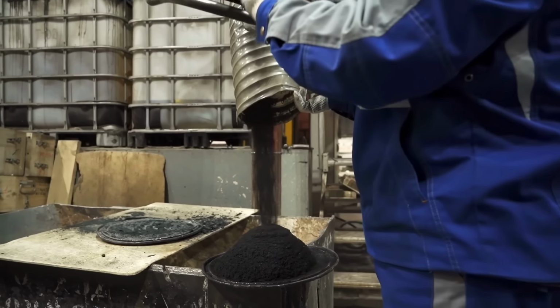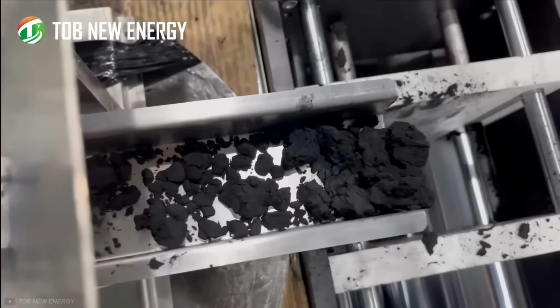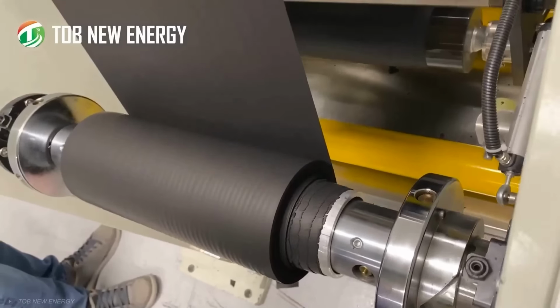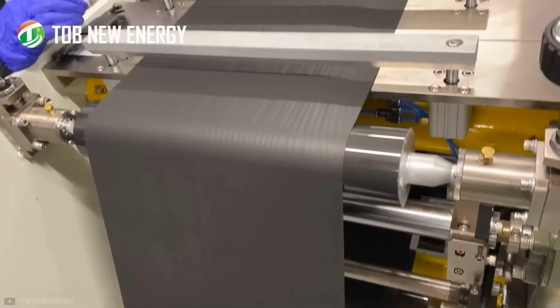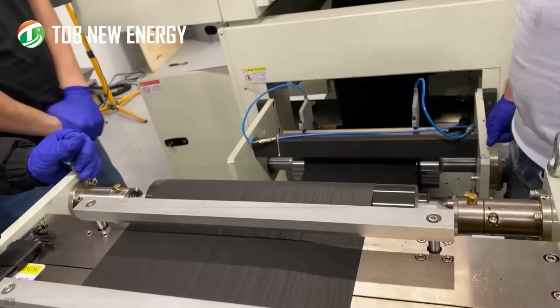But now back to how Tesla cracked dry electrode manufacturing and what that means for cell performance. Okay, so from my research, the big thing that's really stopped the scaling of dry electrode manufacturing has been that cathodes have been particularly tricky. A battery's anode is made from much softer and less reactive materials, but applying the dry process to cathodes has often led to unwanted side reactions and even damage to the production equipment.